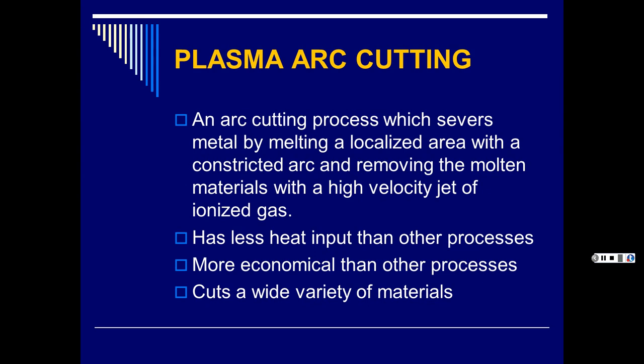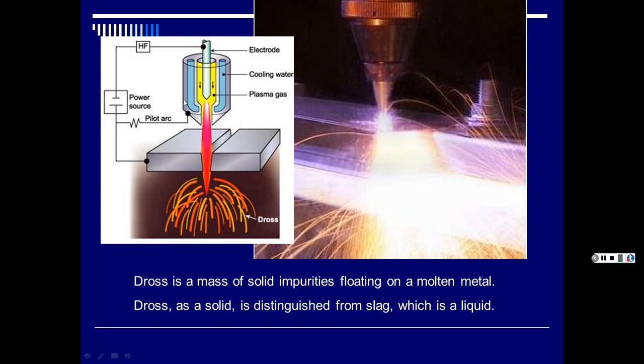I've seen these things where they set them up as a CNC machine. And it goes back and forth on an XY axis and cuts stuff out nice and neat. And it gives you a nice smooth cut. So it's a lot better than your oxyacetylene cutting. And it shows you, again, because it's plasma, 30,000 Fahrenheit and higher. It gets you a real hot stream of ionized gas. And it makes for a thinner cut and a smoother cut. And all the extra crud that comes out is called the dross. The dross is a mass of solid impurities floating on a molten metal. So the dross as a solid is distinguished from slag, which is a liquid. They talk about dross, so that way you know.